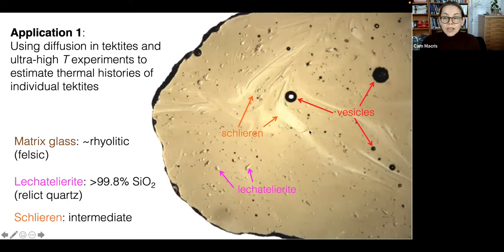Something I want to point out is that entrained in the matrix glass, this rhyolitic felsic matrix glass, we see some local heterogeneities. First I want to point out these little tiny blebs that are speckling the surface. These are almost pure silica glass, or SiO2 glass, and they're called Lechatelierite. And at the end of this talk, everybody's going to have to pronounce it. Just kidding. What these are, are relict quartz grains. So these used to be quartz grains. They were melted by the heat of the impact, but they did not fully homogenize with the rest of the melt. So now they're silica glass. And then these flow bands here are called schlieren, and they're intermediate in composition between the pure silica glass and the rhyolitic felsic glass.